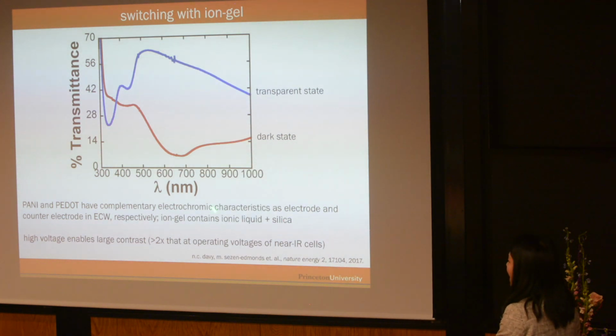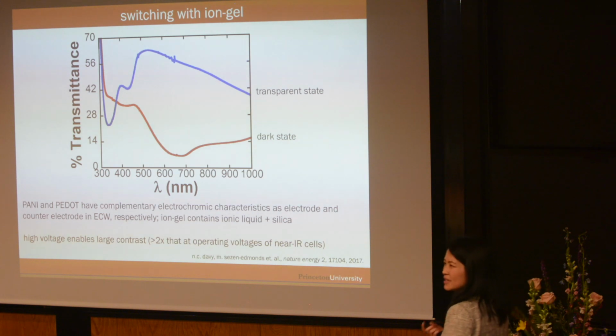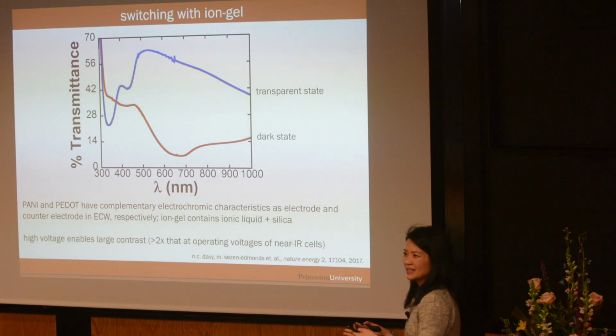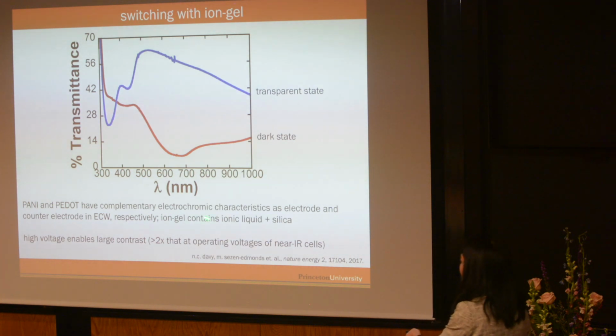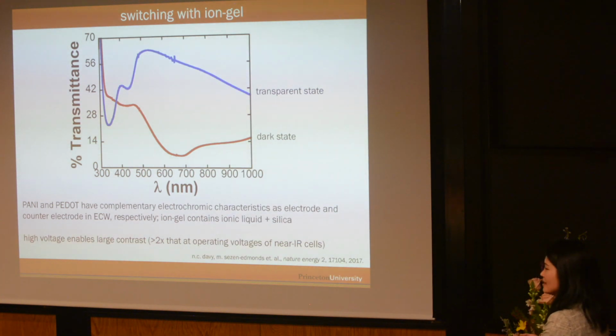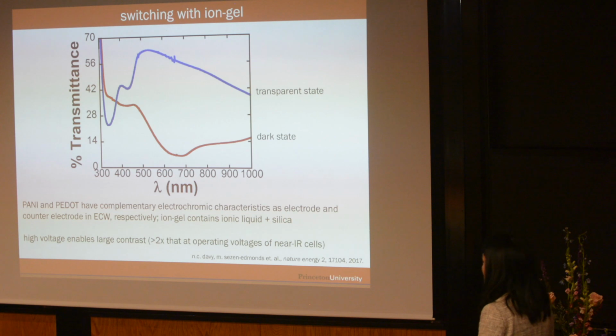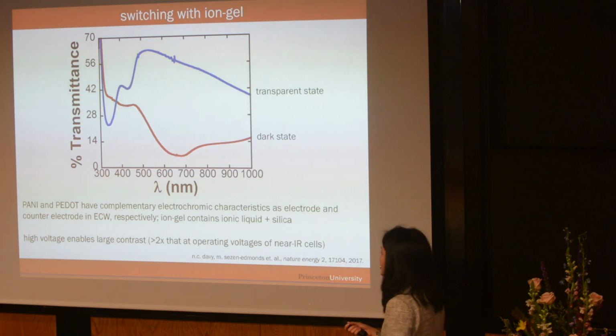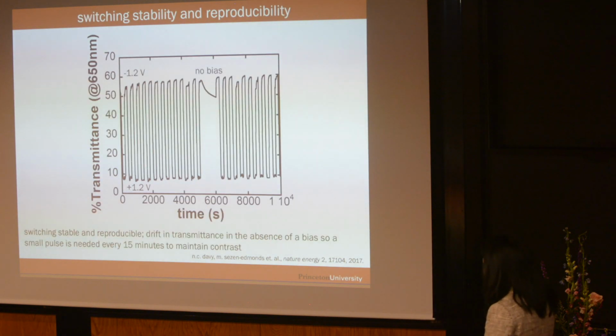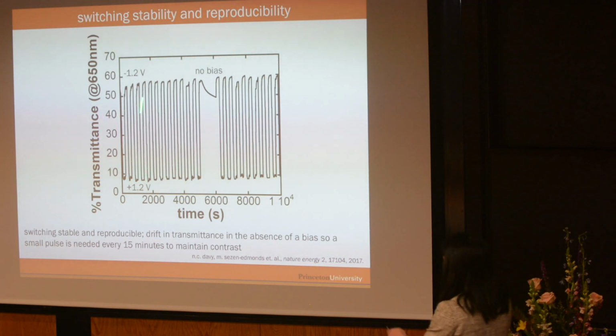Here we're using an ion gel, simply because when you make a window, you don't want a liquid electrolyte, right? Just in case it leaks, it's going to go all over the place. So this is a solid, it's a gel. And it's really with silica, so it's very simple. Because we have this high voltage, and the contrast is now proportional to voltage, we can actually access very high contrast. So this is to show switching with our window. And you can, again, switch back and forth, back and forth, back and forth.